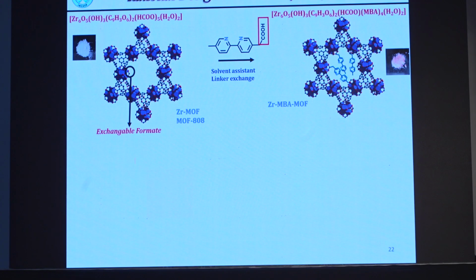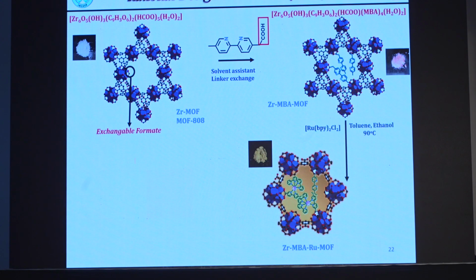Simple coordination chemistry, all of you know coordination chemistry. So you have the COOH. Now I have in the pore a bipyridine ligand. So now what I did, I put the ruthenium bipyridyl Cl. Ruthenium bipyridyl, very classical inorganic coordination compound, all of you know, is extensively used for different applications because of its long excited state lifetime, because it shows the 3MLCT absorption. So now I put the ruthenium here, and then I have the free bipyridine here.